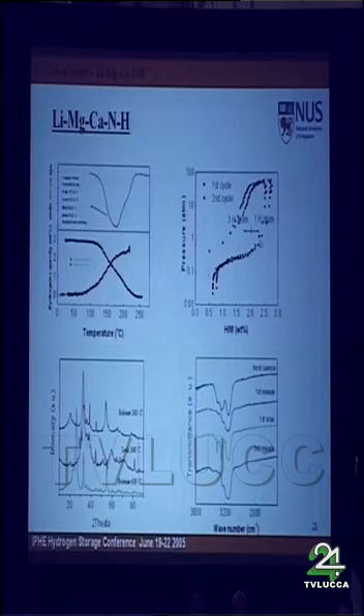There are quite a few interesting results. However, the thermodynamic parameters seem not to improve much compared with the lithium calcium system. We will continue our research in this area, and hopefully we can reduce the lithium content and also decrease the heat of reaction to shift the reaction temperature from 170 to below 100 degrees Celsius. And I also like to point out that every chemical reaction normally will give us a new solid material. It can be an imide, or a nitride hydride, or a new nitride.